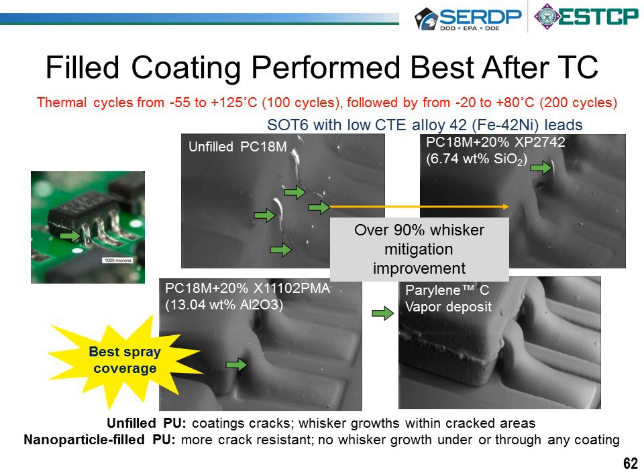And, of course, our Parylene C for reference, you can see it coated everything. There was no thickness buildup. There were no unfilled regions. So that was, as usual, the excellent performance that the Parylene gave us.